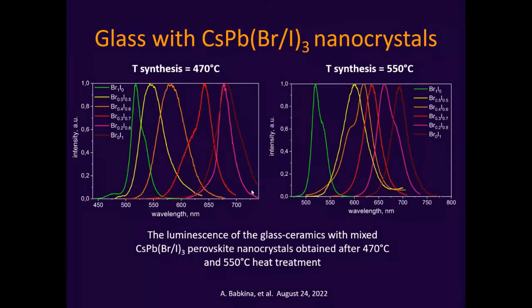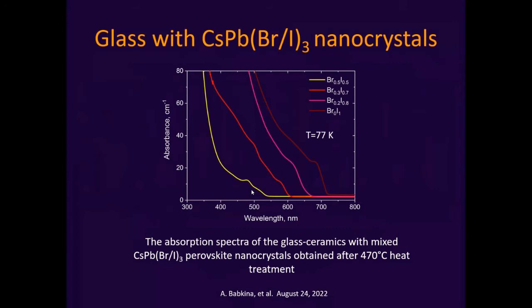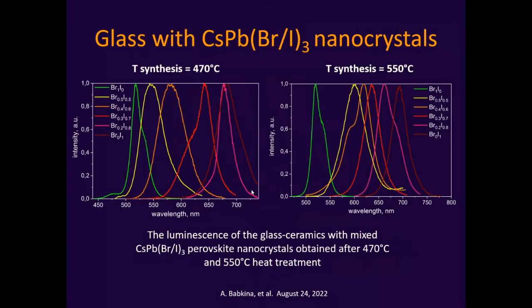So these are luminescent spectra of these mixed perovskite nanocrystals. As you can see, they shift from almost 500 nanometers up to 700 nanometers, so we tune 200 nanometers. What about absorption spectra? It is really very interesting, because when we are talking about mixed nanocrystals, we really don't know if they are mixed inside of the glass matrix. It means that, for example, these crystals may not be mixed, but just sitting inside of the glass matrix simultaneously, but separately. In this case, they can produce 2 bands of luminescence, but you have seen that we have only 1, though in some cases we have 2.